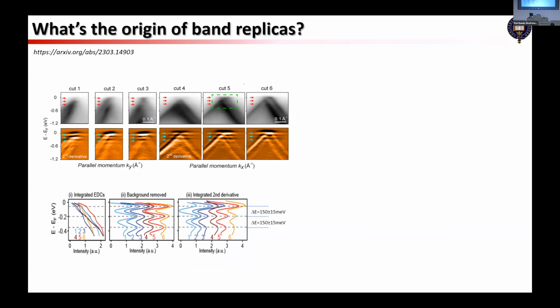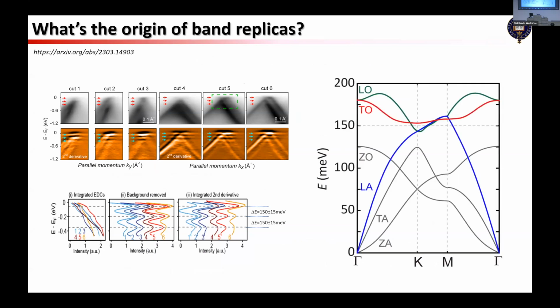This is pretty high. And well, this is the energy uncertainty in the nano-ARPES measurement. And well, this is the phonon spectrum, but before we got to this point, we thought about whether it could be caused by the plasmon. But the sample is very, very weakly doped, so the Fermi surface is very small. The plasmon's frequency cannot be as high as 150 meV.